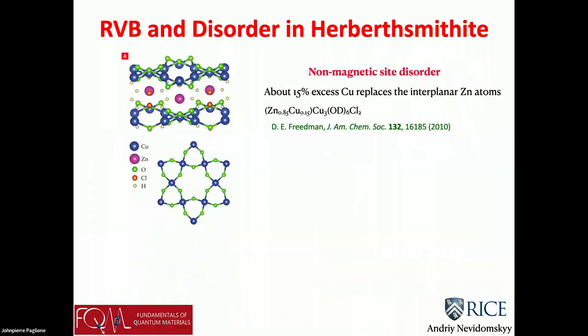Except there was a problem. And the problem was, it turns out, and again, you guys know this better than I do, I'm a theorist, that there is an unfortunate chemistry problem: copper and zinc have very similar atomic radii. And in this compound, unfortunately, there is so-called non-magnetic site disorder. Because of this, 15% of the purple zinc atoms that sit between the planes, on average, get replaced by copper. Now, why is that a problem? It's because copper, unlike zinc, carries a spin. So Pazel just told you in the previous talk, if you remember, that zinc has a fully filled shell, so it doesn't have a local moment. If you replace it with copper, you have an extra spin.